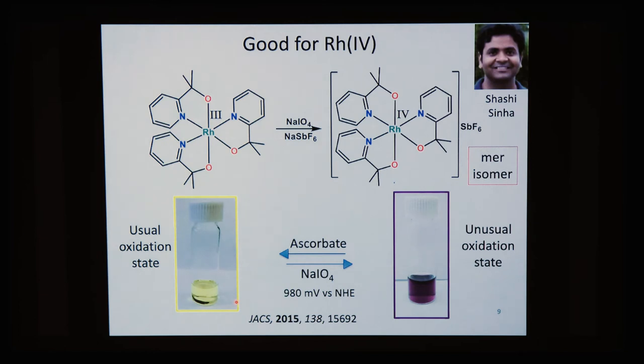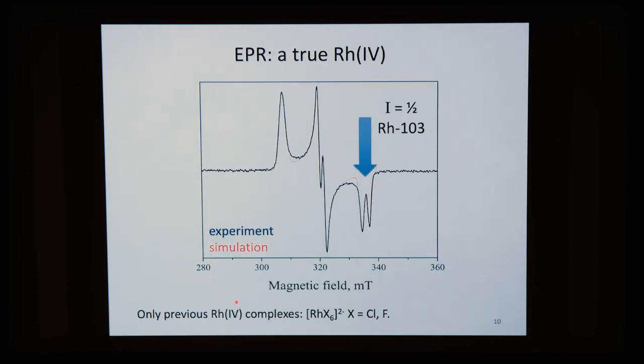So Shashi was able to get that compound nicely and characterize it, including the EPR, because one of the features of high oxidation states is that sometimes it is the ligand which is oxidized and not the metal. And so we need to verify that the rhodium is the oxidation center. And this is shown by the width of the signal here, and also the rhodium-103 coupling shown with the blue arrow. So those verify that this is an authentic rhodium-4.